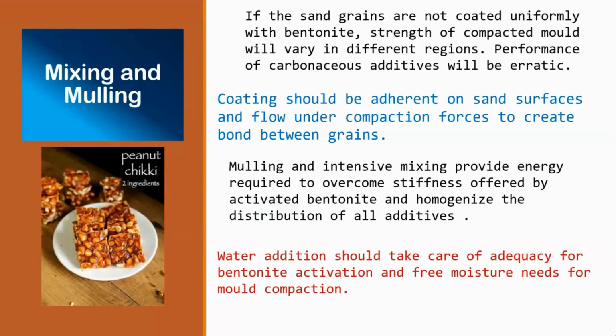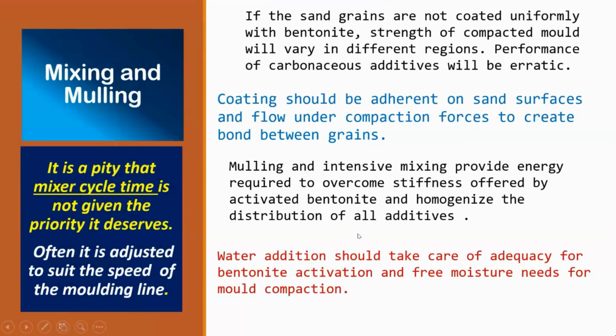It's a pity sometimes the mixer cycle time is not given the priority it deserves. Often it is adjusted to suit the speed of the molding line. What it means is you have a requirement of molds, and I have a molding machine which can produce, say, 40 molds or 60 molds or 100 molds, 200 molds per hour. Then you require that much sand to make those molds. So the demand for the sand increases. The general tendency sometimes is to cut short the mixer cycle so that it can meet the demands of the molding. So this is a fallacy.